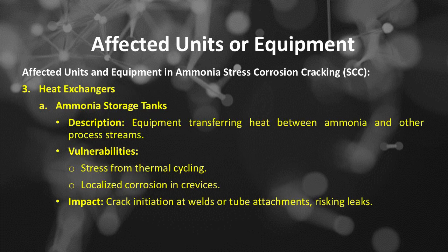Number 3 of affected units and equipment in ammonia stress corrosion cracking is shell and tube heat exchangers. This equipment transfers heat between ammonia and other process streams. The vulnerabilities of these shell and tube heat exchangers include stress from thermal cycling and localized corrosion in crevices. The impact would be crack initiation at welds or tube attachments, risking leaks.